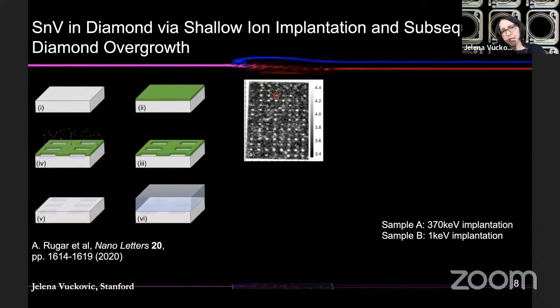So to eliminate that, what we do is we instead implant our atoms at low ion implantation energies. We bring it down from 370 kiloelectron volts to 1 kiloelectron volt. And we start with high purity diamond. There are two things that happen in the process. The first one is you don't damage the lattice anymore because you use very low energy ions.